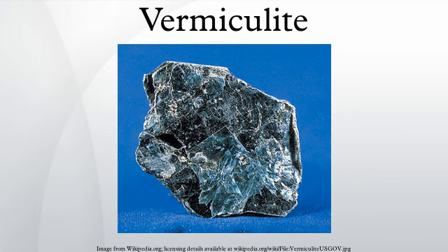Such parts can withstand service temperatures of up to 1150 degrees Celsius and are often used in the aluminium smelting industry as backup insulation behind the carbon cathode in the pots which contain the molten mixture of cryolite and alumina. The molded shapes and boards are used in open fireplaces, high-temperature or refractory insulation, acoustic panels, fireproofing of structural steel and pipes.